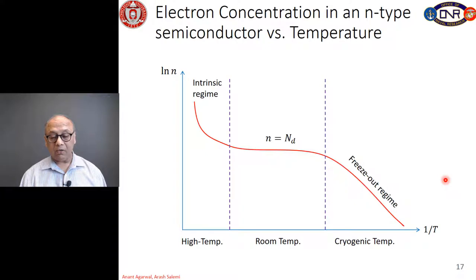All right, so now let's consider the concept of freeze out. And so we know that if let's consider a material which is n-type, so we know that at room temperature n is equal to Nd, which means that number of electrons are equal to the donor density. Now, as we start lowering the temperature, some of those donor atoms will not be able to donate an electron to the conduction band because the temperature is low. They don't have enough energy to jump from the donor state to the conduction band. So in that case, the number of electrons reduces as we reduce the temperature, and that's called the freeze out.